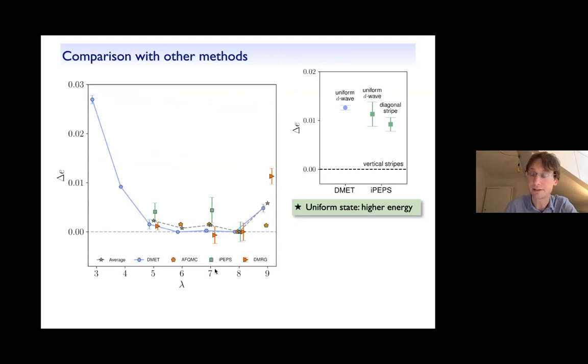So let me show you the comparison here. So let's first focus on this plot here. Here I show you the comparison between the uniform state and the stripe state. And here you see that DMET consistently predicts that the uniform state is about 0.01 t above the stripe state. So that's consistent with iPEPS. And then here you see the energy difference with respect to the lowest energy state for different stripe periods. And you see that all approaches consistently predict a very strong competition between period 5 and period 8 stripes, with maybe a slight tendency that period 8 stripes are favored here.